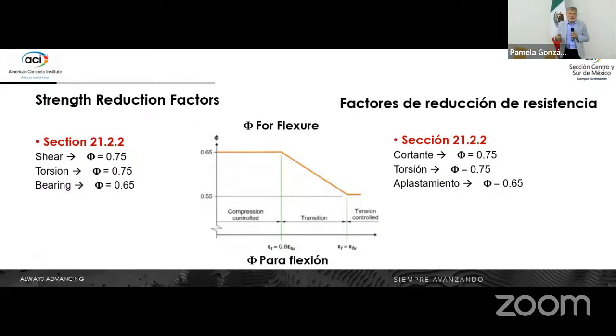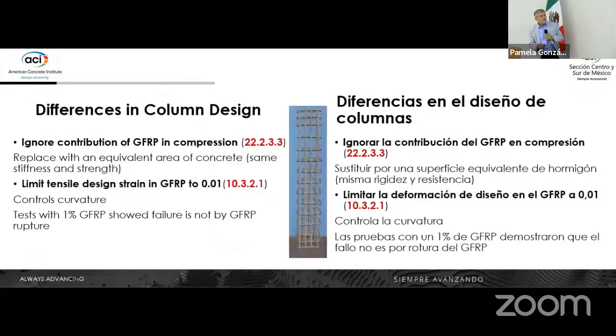Which is unheard of in the case of flexural elements. Obviously, we allow failure in compression in columns, and that's why the phi factor in that case is 0.65, and it degrades to 0.55 if you have a failure in the FRP itself. So in columns, we're even more conservative. We disregard the stiffness of the GFRP and replace it with an equivalent area of concrete. And again, we also limit the tensile strain because we want to maintain the deformability at acceptable levels.